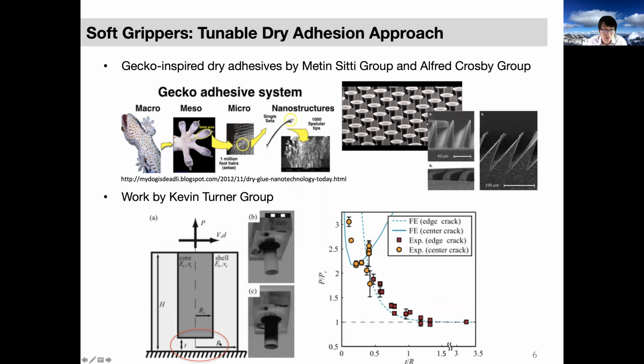Basically, if you don't have the core, you're going to have a stress concentration at this corner, and clearly you're going to have an edge crack. But if you have the core, you alter the stress distribution, and the crack will more likely happen here. So they have this critical parameter T over R, which is the x-axis in this plot. When you change this T, you alter the stress distribution on the interface, and the mechanism I described will kick in, and that will be responsible for the increase of dry adhesion of the structure.